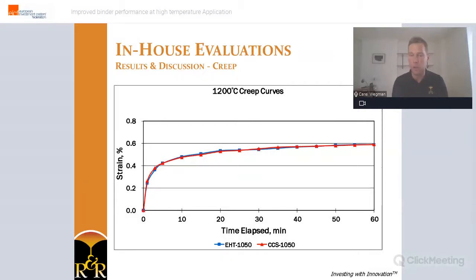1050 or lower. Given the fact that the typical firing temperature for commercial foundries is around 1000 degrees C, we believe that they will probably not find EHT binder a useful solution in resolving creep-related issues such as delayed leakage or hot deformation.